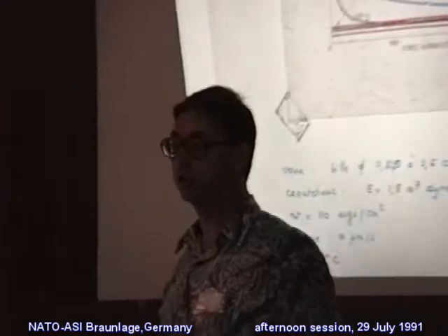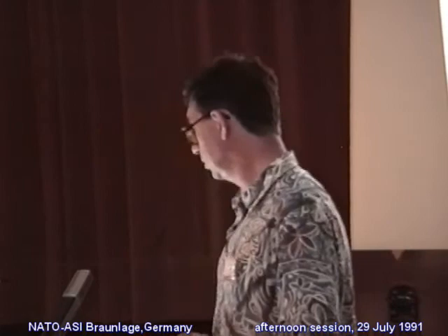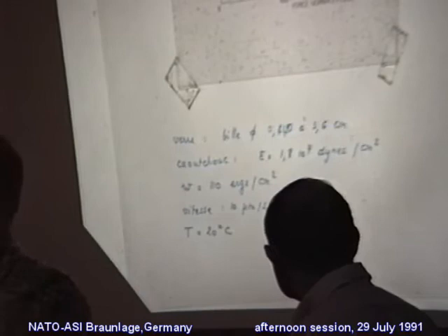This is an example of friction coefficient of a glass ball on a rubber, for various radii of the glass ball. And you see that when the load decreases, the friction coefficient can increase until 70 or even to infinity, because we have a friction force under zero load, so the friction coefficient is infinite. And we have to take into account the supplementary load due to the molecular forces. And one way to do this is to use the load P1 given in the JKR theory, which gives exactly the same radius of contact.